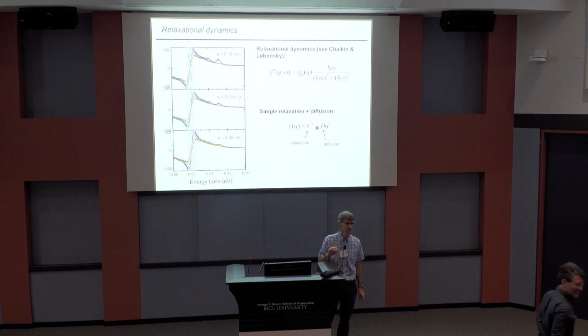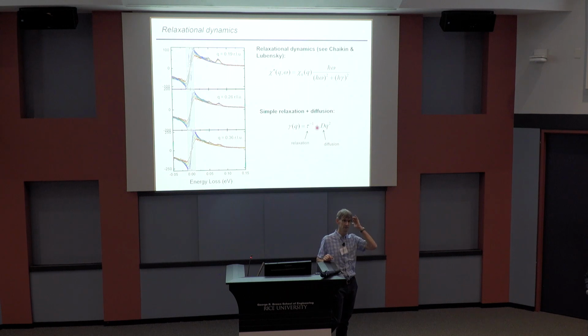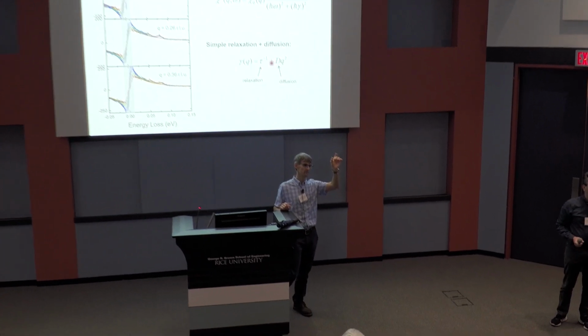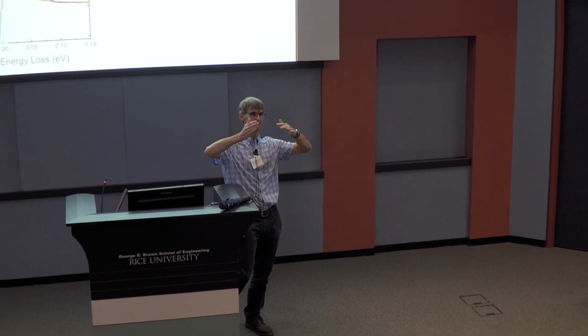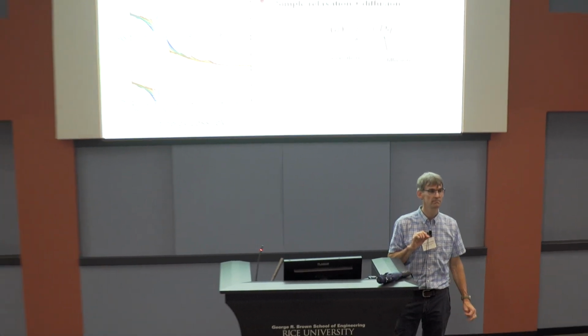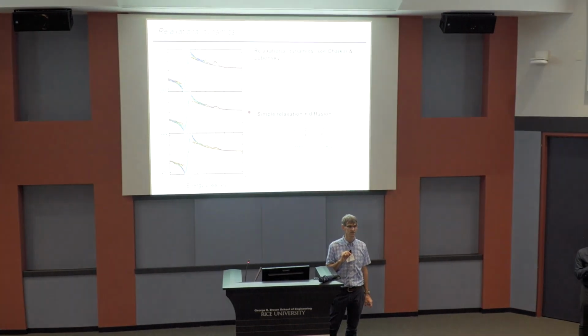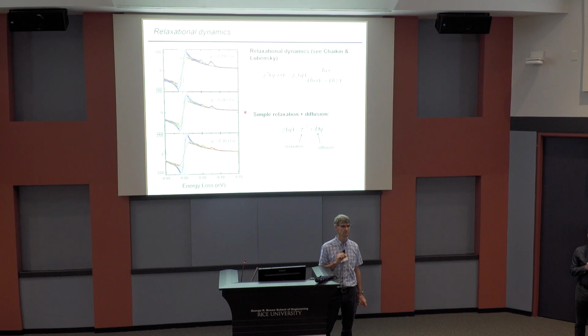What's the lowest frequency that you actually access? I mean, we go through 0, but there's a finite resolution. So the resolution width is about 6 millivolts. As you get closer and closer to that, it's a question of when do I stop believing the data, and that's what the shaded area is. Down to where did you use the data for your analysis? We fit everywhere except where the gray box is. So we fit this region here and above. And then below that, it just happens to look okay. So like 10 meV. Something like that.